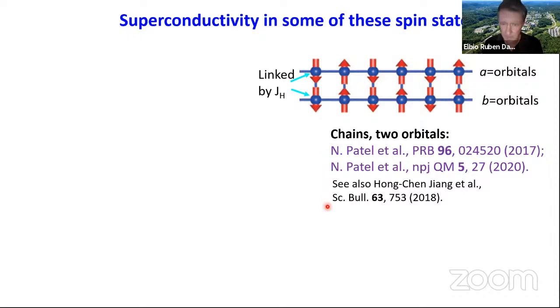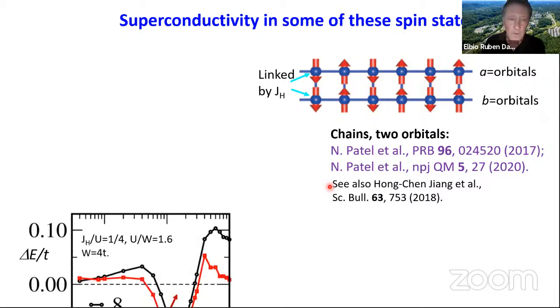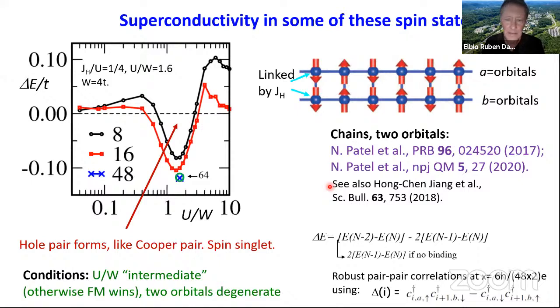There is another work independently done by the group in Stanford and Berkeley. They reported similar results. So this is what we found. I'm showing you just a tiny fraction of what we found. What you see here is I'm changing the Hubbard U. I'm working at a ratio of Hund coupling over U, which is fairly robust. Intermediate range couplings, not very large U. At very large U, nothing has any tendency to superconduct.